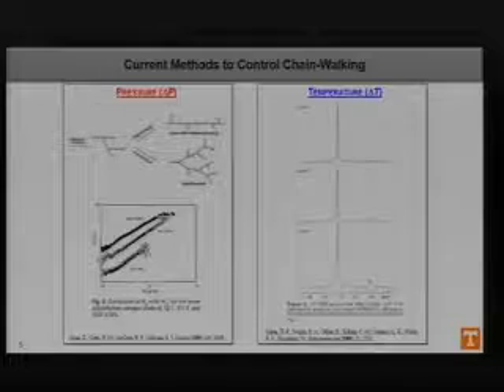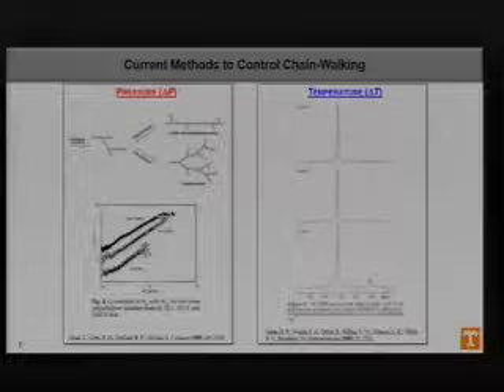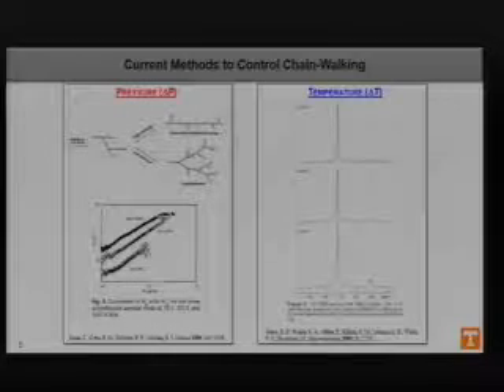The other method that we can use to control chain walking is temperature, in which from the proton NMR I have shown here, this very large peak corresponds to the protons in the backbone of the polymer chain. And this very small peak to the right that continues to grow in represents protons that have appeared on branches off of that backbone. So as we increase the temperature, we can also increase the branching. Now, both of these methods are external controls.